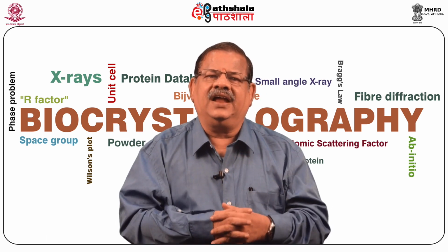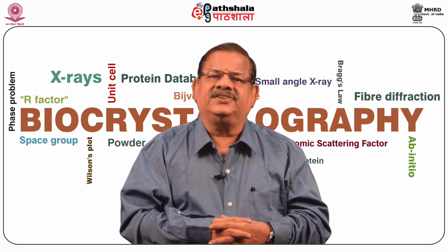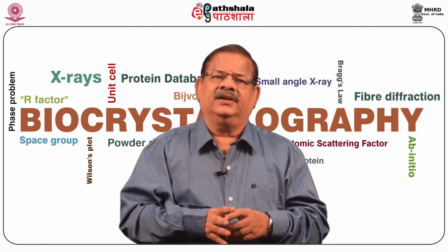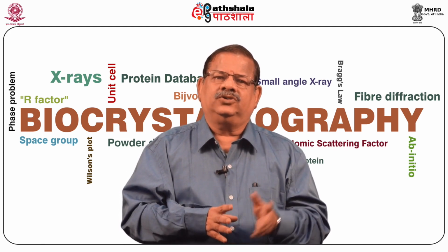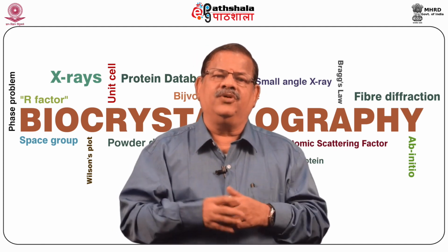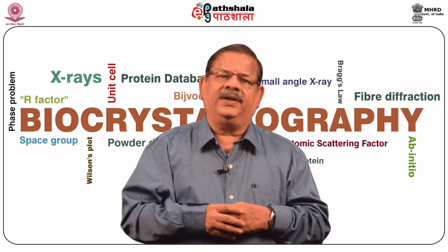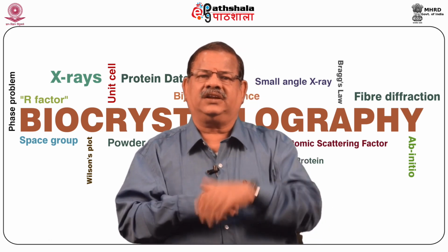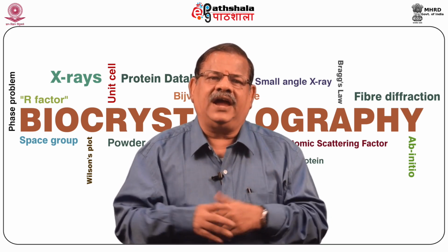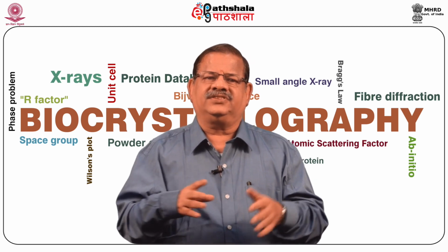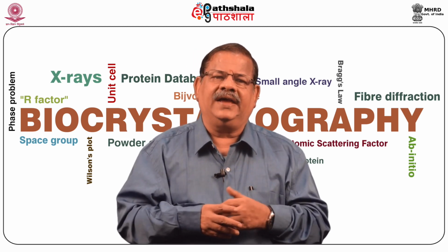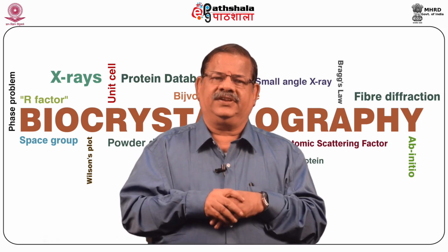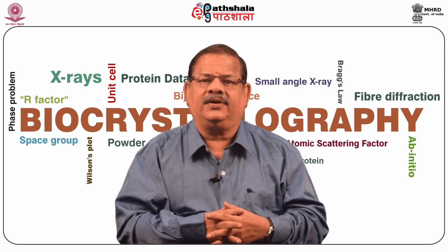If this length is L and capital R is the distance of the point of measurement from the specimen, the ratio of the energy in the length L to that in the whole halo is obviously L over 2 pi R sin theta, and hence the energy diffracted into a short length little l of the halo compared with the intensity of the incident beam is given by P over I, which will be equal to p L Q V over 8 pi R sin theta, as given by equation 29.7.